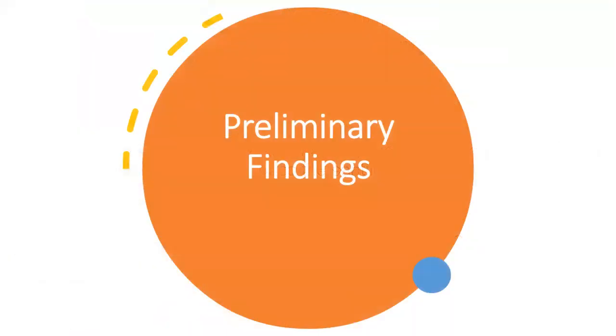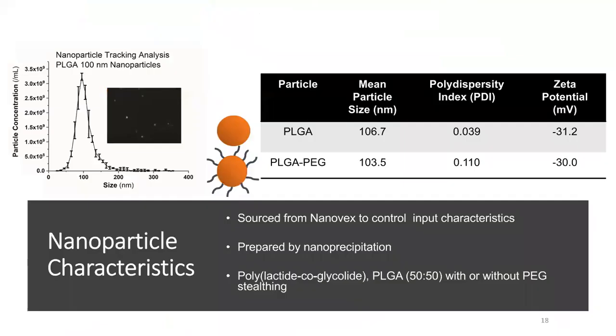And now here we get onto the fun bit, and it's here where I get to talk about the first set of data they've collected in the lab. So this first slide shows us what the nanoparticles look like without the protein corona. These are effectively shop-bought nanoparticles, and we can see that they are both approximately 100 nanometers in size via DLS. And in-house, we've also confirmed this size by nanoparticle tracking analysis too. And they've both got really narrow size distributions and are both moderately negatively charged.